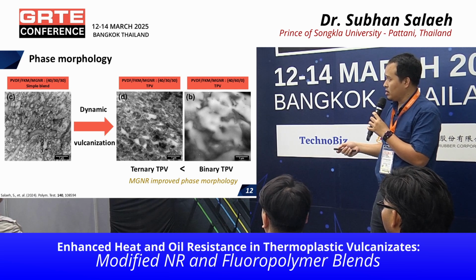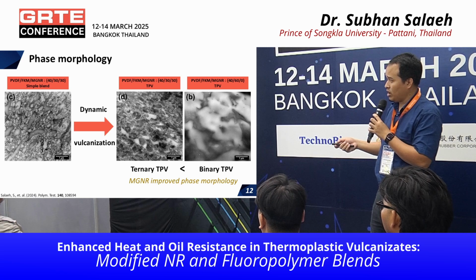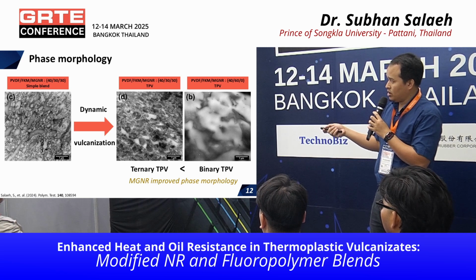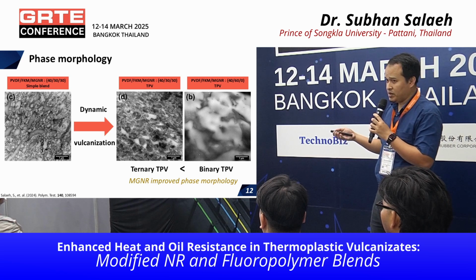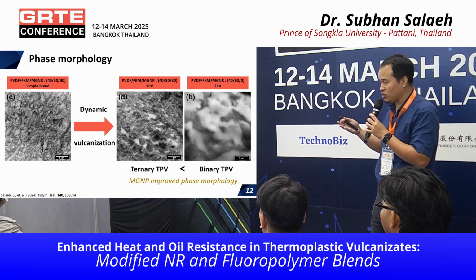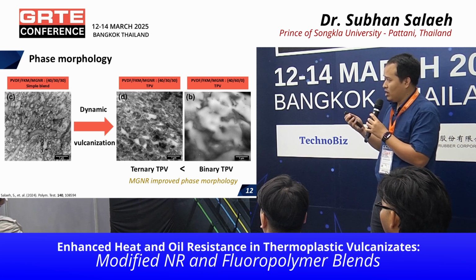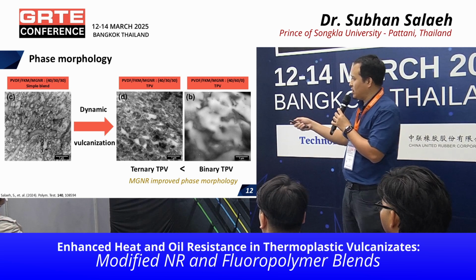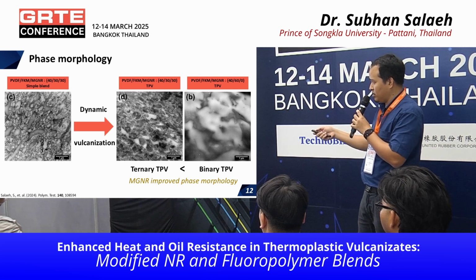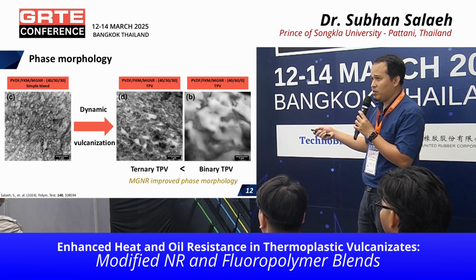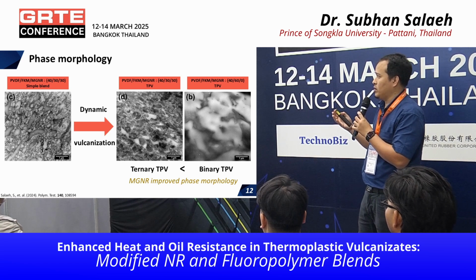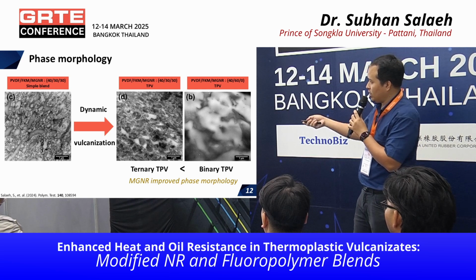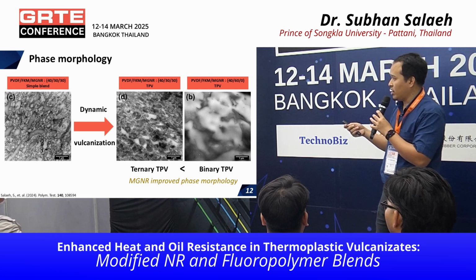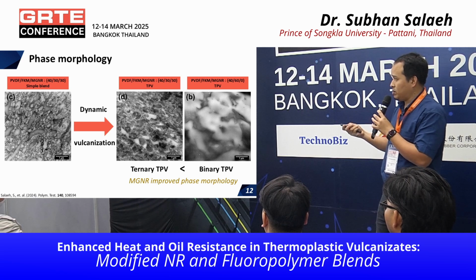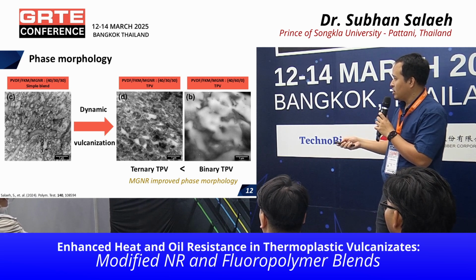And then this is the TEM morphology. On the left hand side is the simple blend. The dark phase is PVDF, and the bright phase is MGNR and FKM, so it's difficult to classify. But after dynamic vulcanization, we can see the phase inversion and the difference between the simple blend and TPV, due to the curative agent in the TPV, which is diamine. So we can see that the PVDF becomes the matrix phase, and the FKM and MGNR become the dispersed phase for TPV.